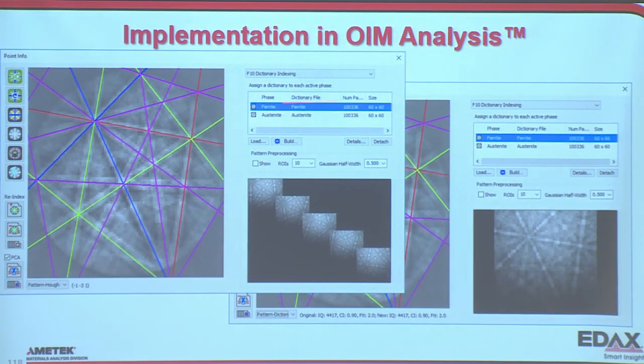Just to show you, it is actually implemented in the software. We load dictionaries here. This is 5 sample patterns from the dictionary. And then we switch this to dictionary indexing and hit our button, and off it goes and does the scanning, and this finds this pattern is the best match. So this is the pattern from the dictionary. This is the experimental pattern.